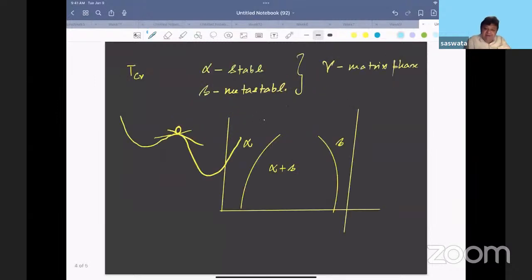So you find that instead of finding the intercept, sometimes we have to find the slopes. Many times the diffusion potential or the change is driven by the slope, not by the exact values. It's not the values that are important, but the slope. How is your energy landscape sloping? If it slopes one way or the other, you can go. If the slope is steeper in one direction, that is where the transition will go. It is not the relative positions of the minima, but the slope that matters.